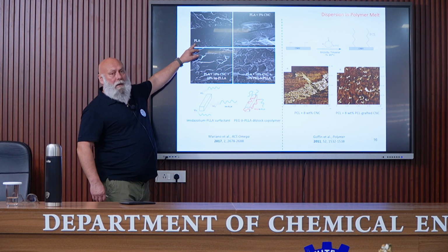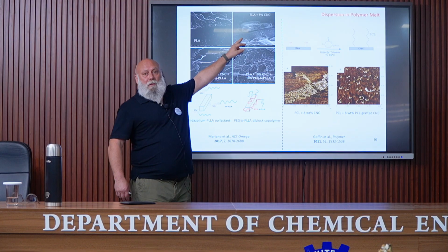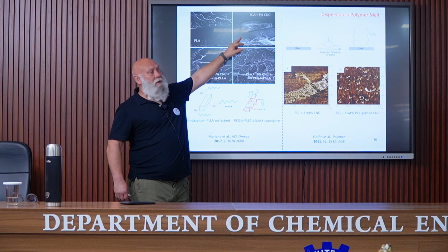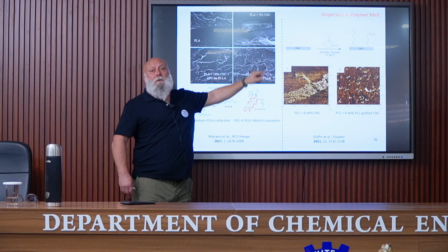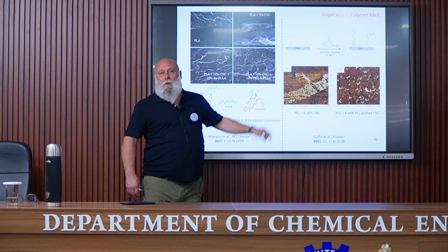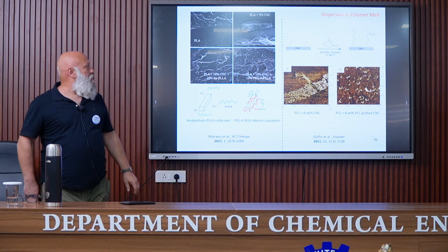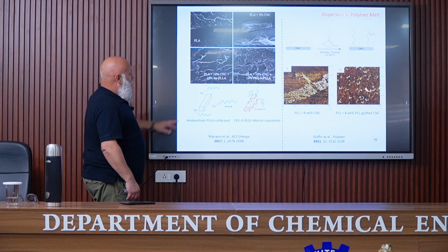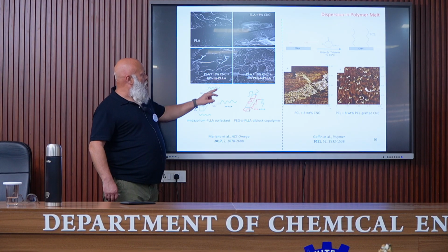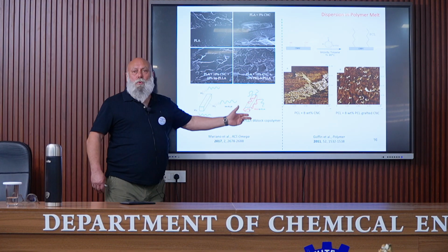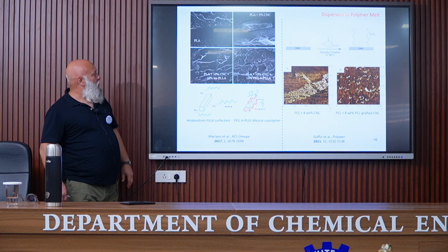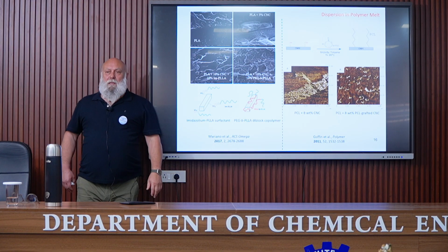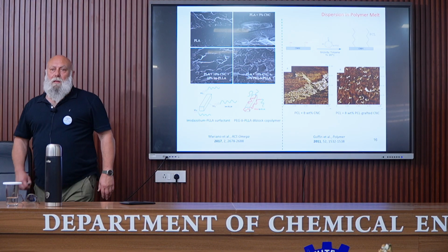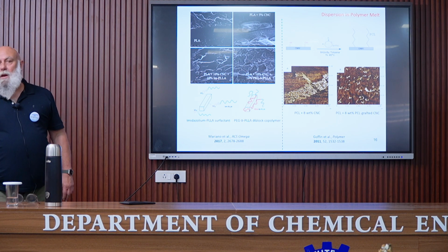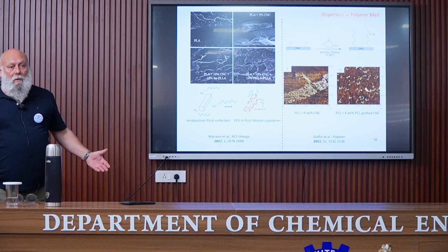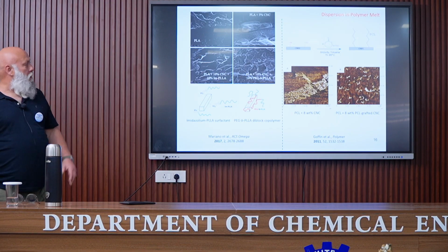This is a pure PLA. PLA with 5% cellulose nanocrystals. You can see here a big aggregate and no interactions between the two elements, between the matrix and the reinforcement. And here with 10% nanocrystals, using these two compatibilizing strategies. We cannot see aggregates, but in SEM, we cannot see individual nanocrystals. So this is an indication that there is no aggregate.